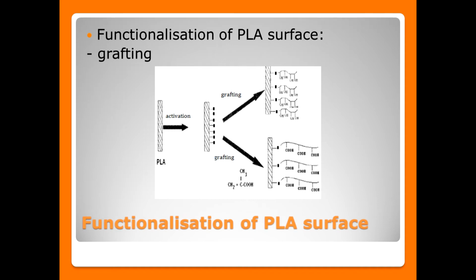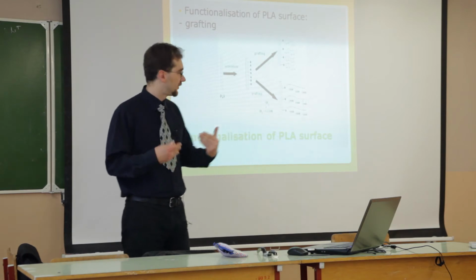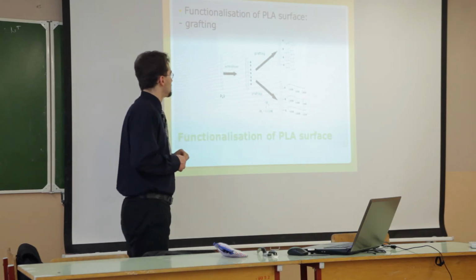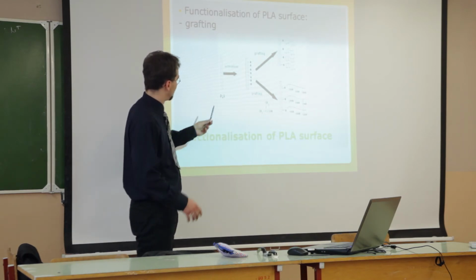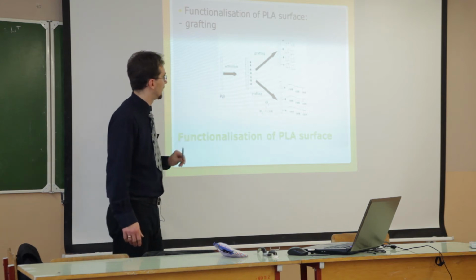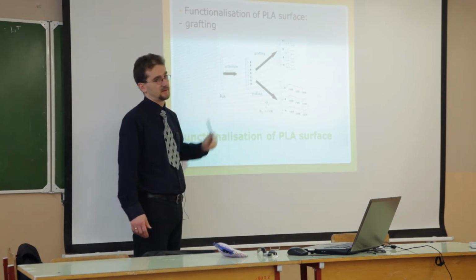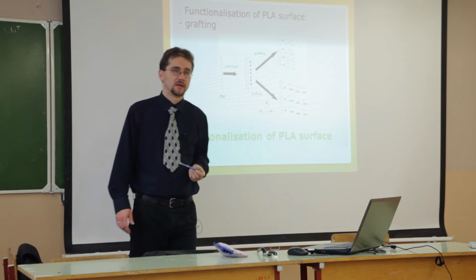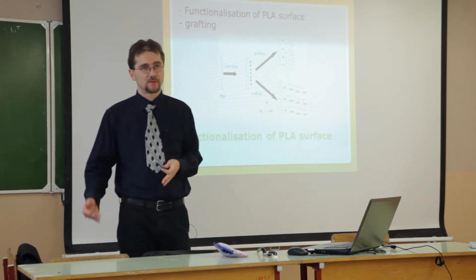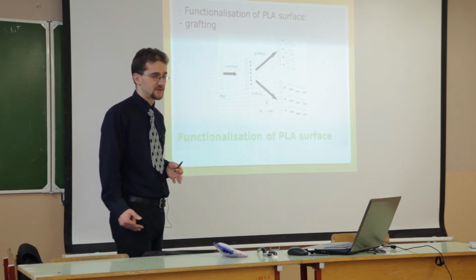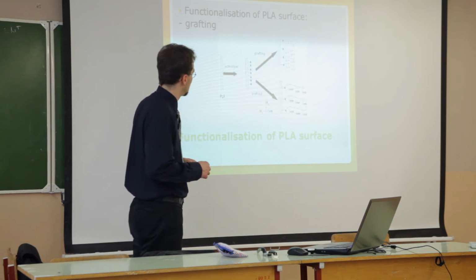It is possible to have grafting from and grafting to. The mechanism is that you have the polylactide, and you make an activation process to have some active groups on the surface. It is not easy; I will show you in the next slides.